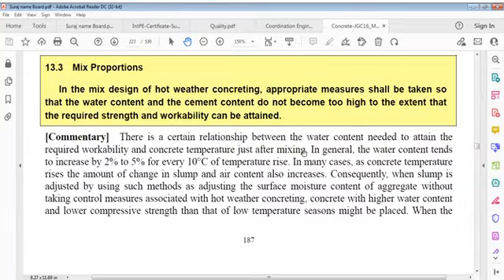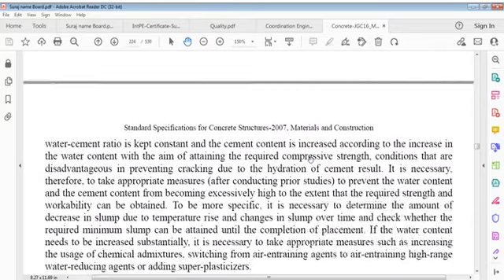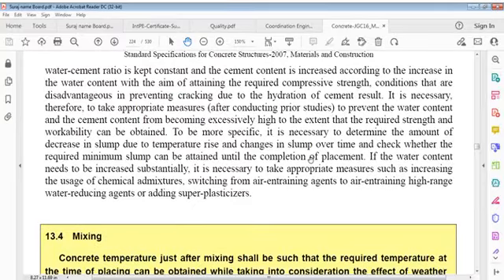Consequently, when slump is adjusted by using such methods as adjusting surface moisture content of aggregate without taking control measures associated with hot weather concreting, concrete with higher water content and lower compressive strength than that of low temperature seasons might be placed. When the water-cement ratio is kept constant and cement content is increased according to the increase in water content with the aim of attaining required compressive strength, conditions that are disadvantageous in preventing cracking due to the hydration of cement result.